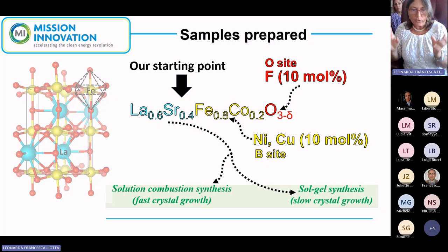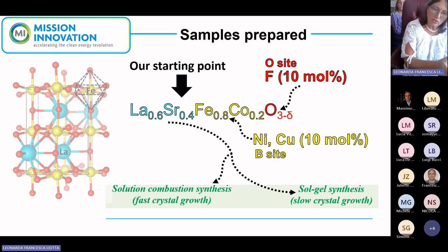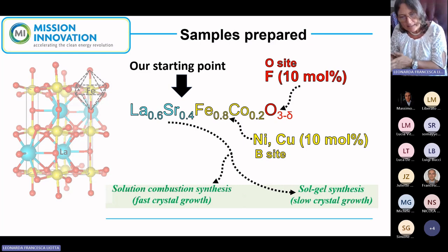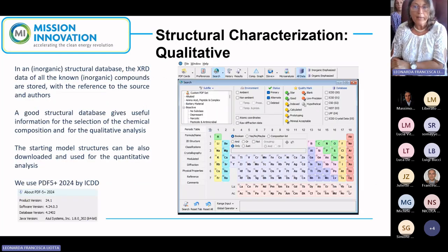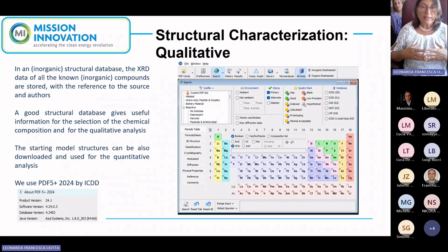The other strategy, as you know, is the synthesis strategy. So we prepare the same compound, the same composition, but using solution combustion synthesis or sol-gel synthesis with citric acid. All these materials, these powders, should be characterized, and the first characterization tool that we use is the investigation of the structure by powder X-ray diffraction. To do that, you first need qualitative characterization, and we use an inorganic structural database where you can find the information on the design stage and on the analysis stage.